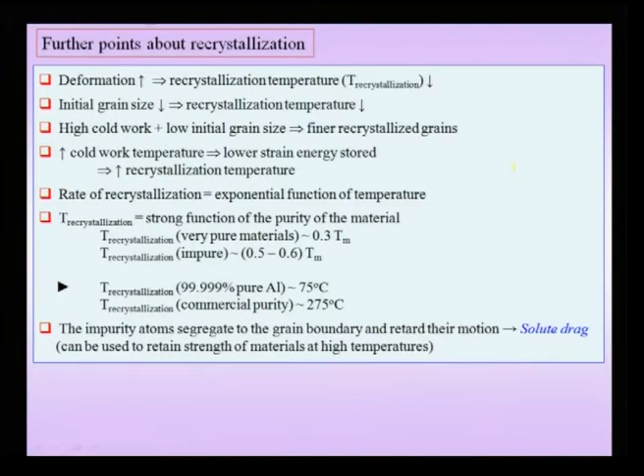Now, if this recrystallization or the working itself is done at a higher temperature, wherein recrystallization can take place actively during working, such a recrystallization would be called dynamic recrystallization. That means that I do not have to have a separate recrystallization step between the working steps. Therefore, I am doing hot working, and again let me warn once more that terms like hot working and cold working are technical terms, and we will be defining them in the coming slides. But the important point is that if I do my working at a high enough temperature that recrystallization is actively taking place while the deformation is in progress, that implies that I do not have to have a separate step wherein I recrystallize the material before I do further deformation.